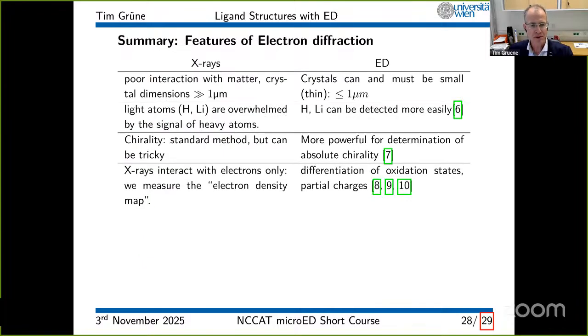This is my summary slide between X-rays and electron diffraction. X-rays interact really badly with matter, and you need quite large crystals. Here I put 1 micrometer because at some sources you get away with a 1 micrometer crystal. The disadvantage is that you don't see these crystals, and crystal separation is a matter of luck. A much more realistic size is maybe 10 or 20 micrometers. For a protein structure, a good size is 100 or 200 micrometer in each dimension in order to have a good data set with X-rays.